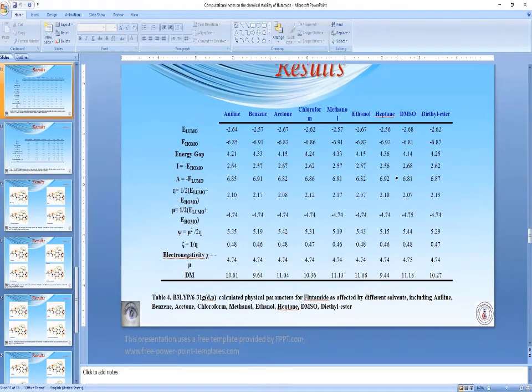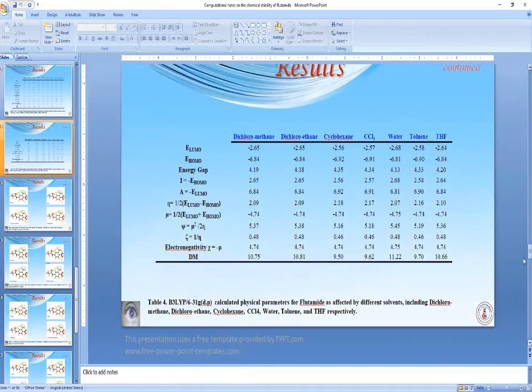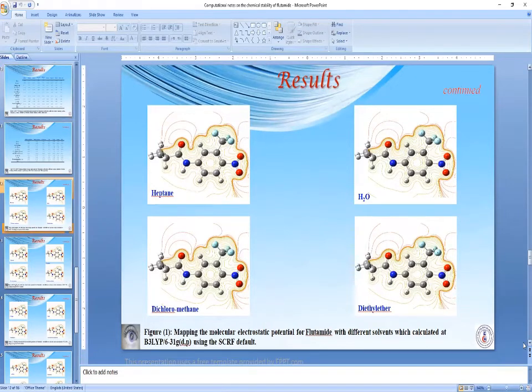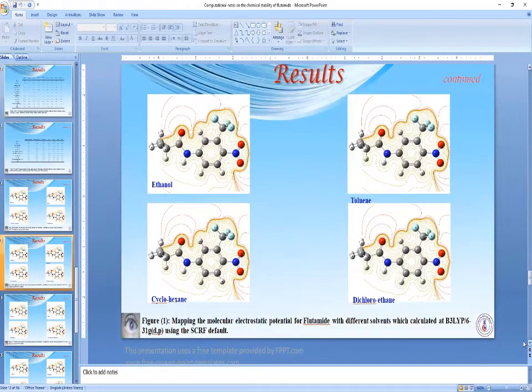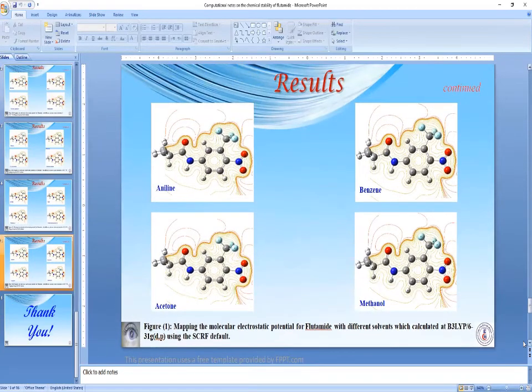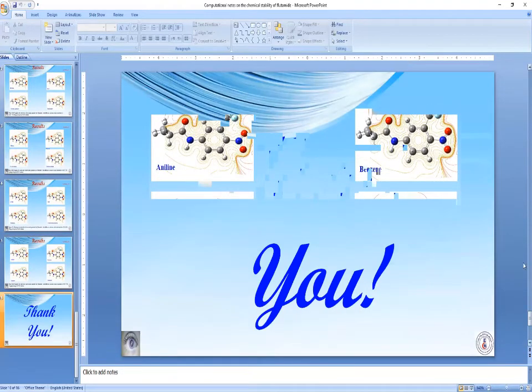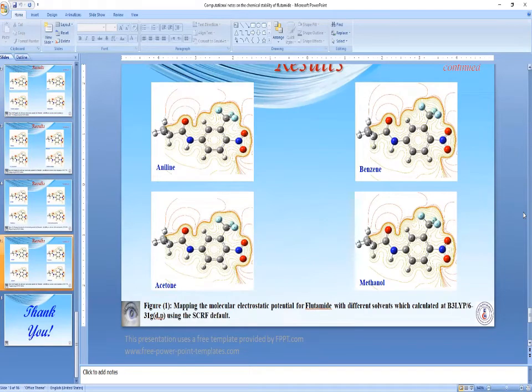Moreover, molecular electrostatic potential has been mapped on the surface of the flutamide molecule in the different solvents. The electrostatic potential, as we can see in different solvents, is invariant. The negative regions of the electrostatic surface potential are mainly localized on both oxygen and fluorine atoms, indicating possible sites for electrophilic attacks.